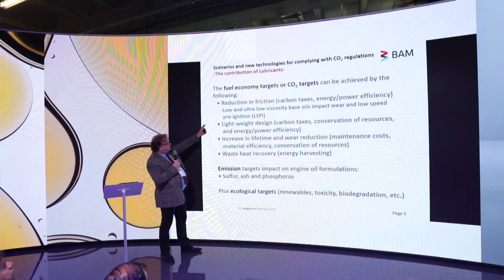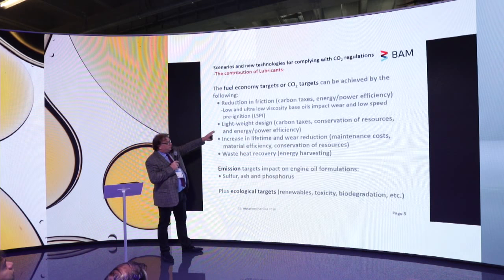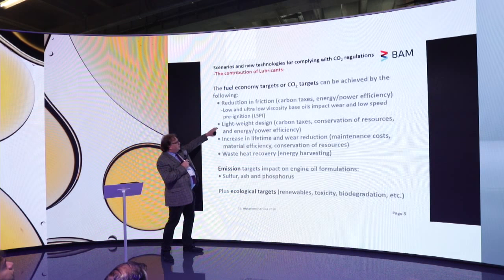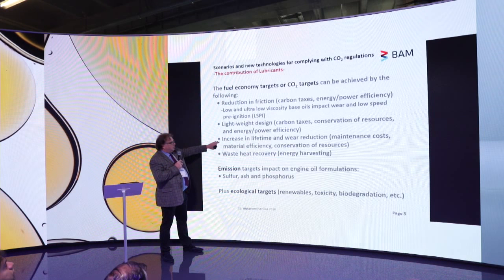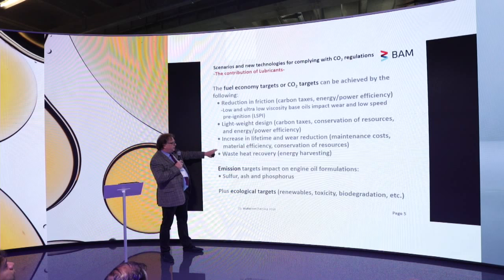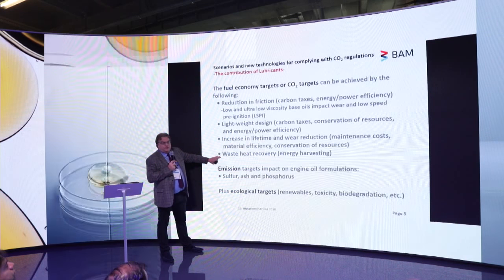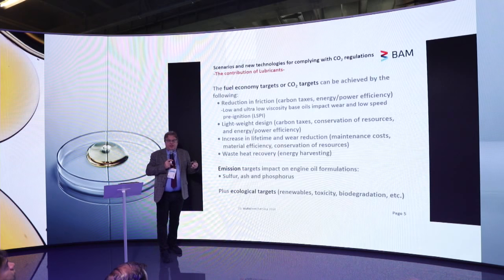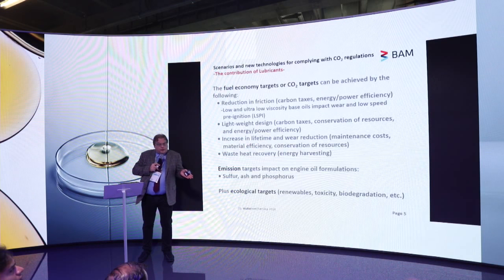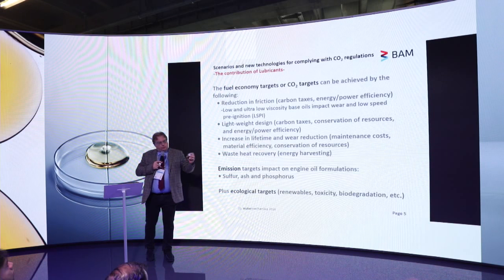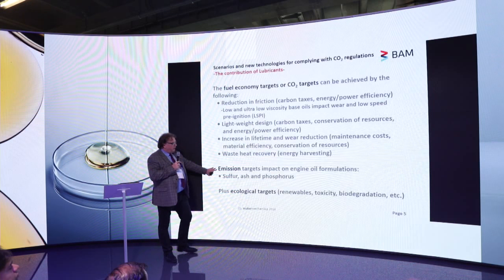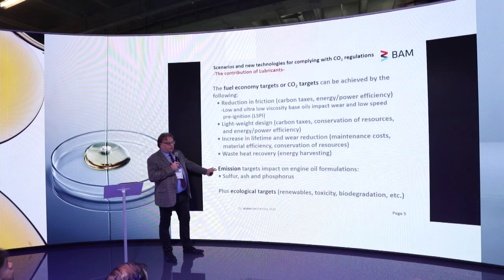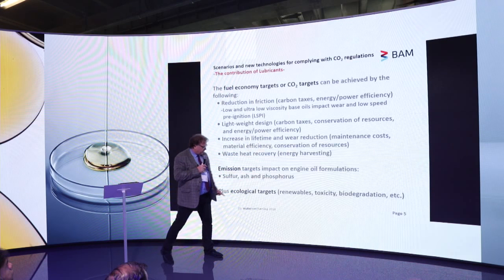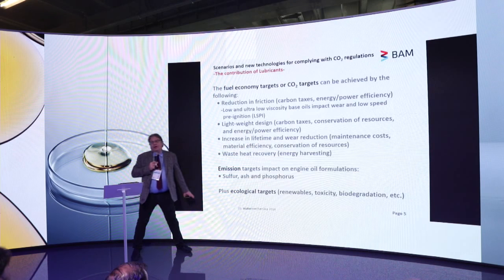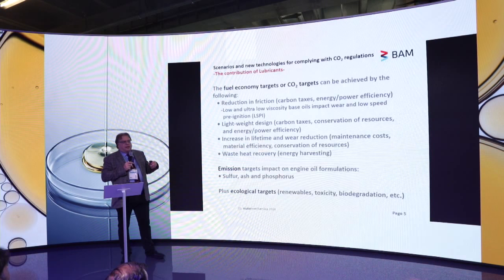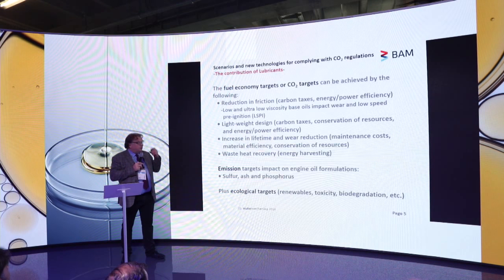And this can be achieved by low or ultra low viscosity base oils, lightweight design, increase in lifetime and wear protection, and also waste heat recovery, because 40% of the heat of the fuel goes into the exhaust. You could recover it. Another problem you have are emission targets related to the engine oil: sulfur, ash and phosphorus. And maybe in the future you will also have ecological targets like a content of renewables, biodegradation and toxicity.